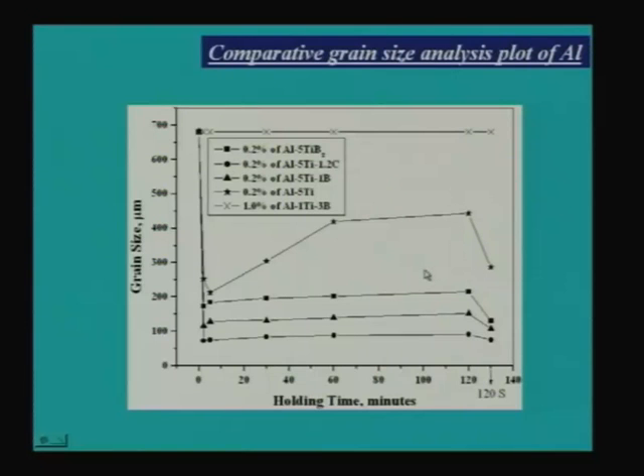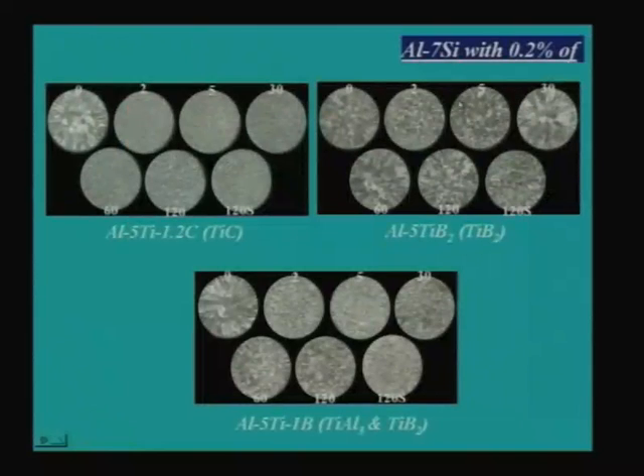So one can talk about the grain size analysis, and this is with aluminum 7 silicon. Usually we know that most of the grain refiners, when you add them to aluminum, you get good grain refinement, but when you add them to aluminum containing certain alloying elements, you do not get good grain refinement. This is what people call the poisoning effect. That means the alloying element present in aluminum reacts with these particles, which you are adding for grain refinement as heterogeneous nucleating sites, and forms some kind of complex particles on the surface of these particles.